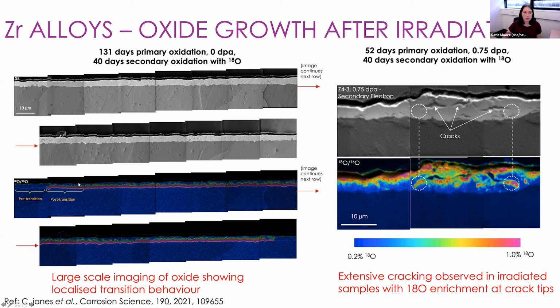So we can describe this oxide here as being post-transition. Zirconium alloys go through a number of transitions where the oxide is either protective or non-protective, and whether the water can penetrate through that oxide or not. Interestingly, just how it happened with the area that we imaged, we found that this region on the side here and over here had not gone through one of these transitions. So we can show that the whole oxide does not undergo transition at exactly the same time point.